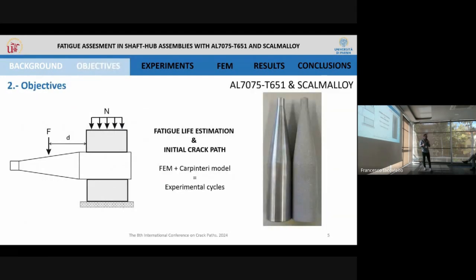So to summarize what we are going to do in this work, we are going to design a rig to do some tests with a configuration like this, to reproduce the shaft-hub assembly. Then we are going to design a FEM model to extract the stress field from it, and then we are going to apply the Carpinteri criterion to predict the crack initiation, orientation, and the fatigue life.